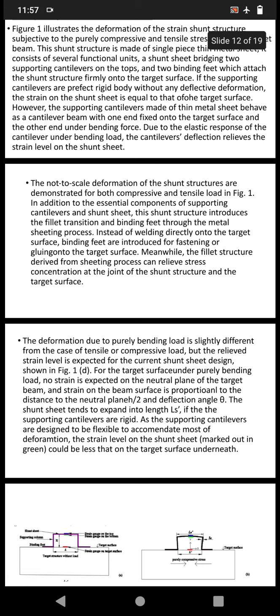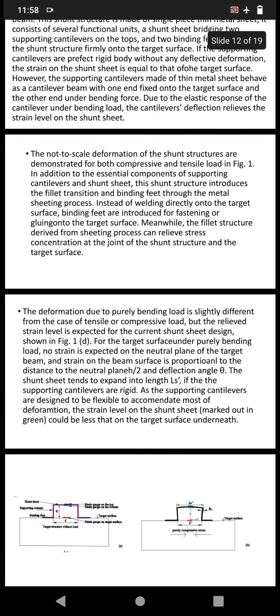The deformation due to purely bending loads is slightly different from the case of tensile or compressive load, but a relieved strain level is expected for the current shunt sheet design shown in figure 1. For the target surface under purely bending load, no strain is expected on the neutral plane of the target beam. Strain on the beam surface is proportional to the distance to the neutral plane and deflection angle theta. The shunt sheet tends to expand to length Ls if the supporting cantilevers are rigid, but the supporting cantilevers are designed to be flexible to accommodate most of the deformation. The strain level on the shunt sheet, marked in green, could be less than on the target surface underneath.